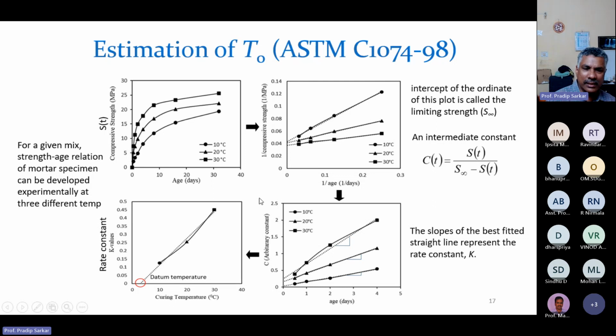So this is the practice. This is the flow of this rate constant K, and we plot that rate constant against the curing temperature, curing temperature versus rate constant. We have three values: 10 degree, 20 degree, and 30 degree. Because we have these three curing temperature values, we get a datum temperature. If we don't calculate this datum temperature, as per code we can assume the value 0 degree as a datum temperature, and